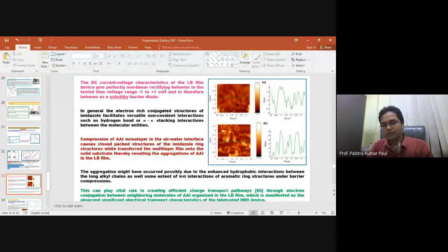The DC current voltage characteristic of the LB film device shows perfectly nonlinear, rectifying, unidirectional behavior, and we tested a bias voltage of -1 to +1. This is the organization of the LB film. You see the aggregated structure here.